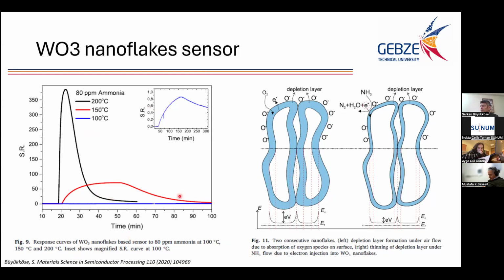And if you look at the mechanism here on the right hand side, you see consecutive nanoflakes. For the nanoflakes, as I mentioned previously, there's a depletion layer formation due to oxygen adsorption on the surface. By the way, this oxygen adsorption, or the kind of oxygen ions, depends on the temperature. So they might be molecular oxygen or atomic oxygen. It depends on the temperature.